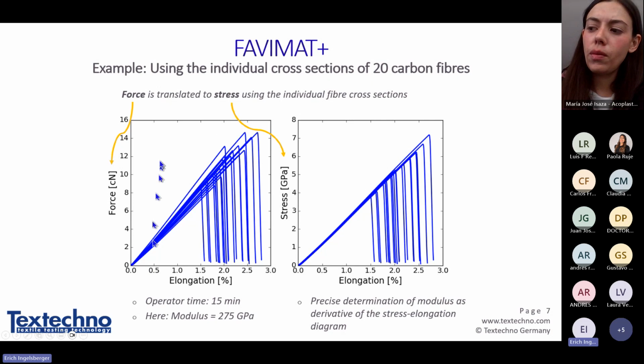This diagram on the left-hand side shows the breaking force over elongation of individual fibers. You have thin fibers and thick fibers, and this results in a certain variation of the force. But if you then relate this to the diameter or cross section we have measured, you will see the variation nearly disappears, because we do this for every individual fiber.